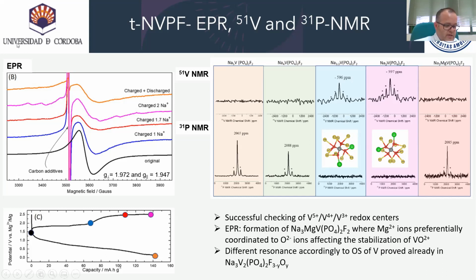On charge, the EPR signal decreases smoothly, appearing diamagnetic vanadium 5+. After charge and complete discharge, the EPR signal is not recovered completely, which is related to the formation of sodium 3 magnesium vanadium PO4 2 F2, where magnesium ions prefer being coordinated with oxygen ions, affecting the stabilization of the vanadyl ion. On the right part, we try to prove the redox property of the vanadium 5, vanadium 4, vanadium 3 active center.